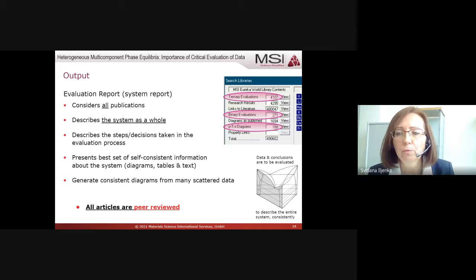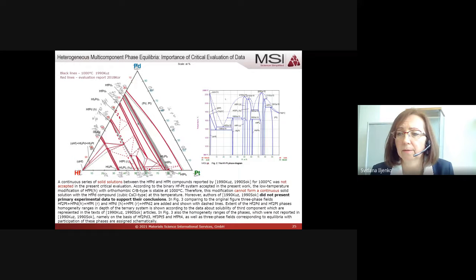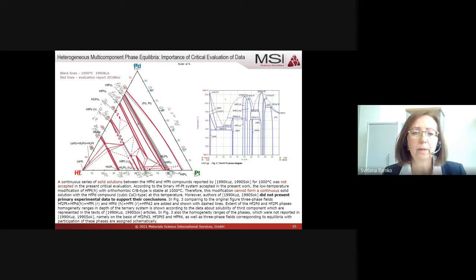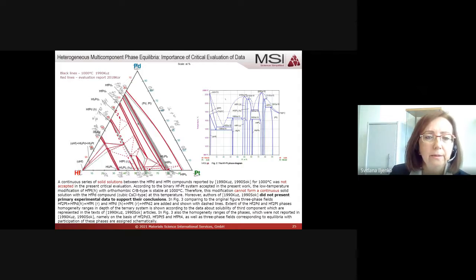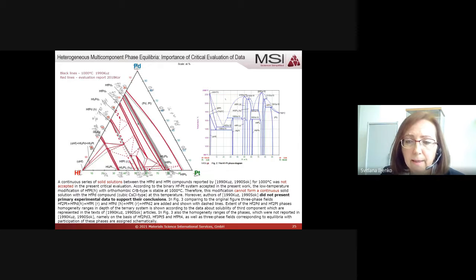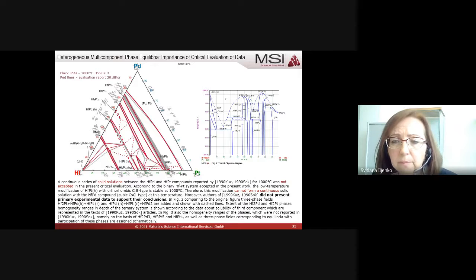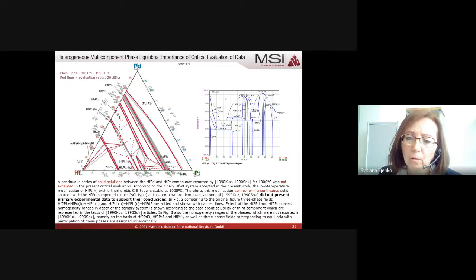Now I would like to show you some examples of how critical evaluation works, or what actually are the results of critical evaluation, what that actually means. So we have here an example, the hafnium, platinum, palladium system. In the year 1990, at 1000 degrees, the black phase diagram was published, which supposed a continuous solid solution between these two stoichiometric phases, hafnium platinum and hafnium palladium. And later, the hafnium platinum binary system was revised, and it was found that the hafnium platinum phase actually has two different modifications, high temperature and low temperature.